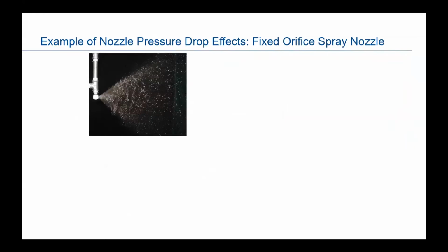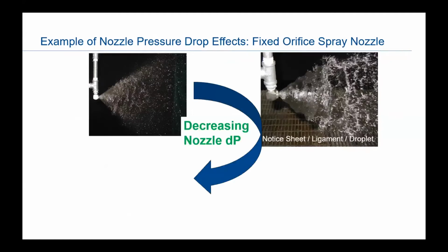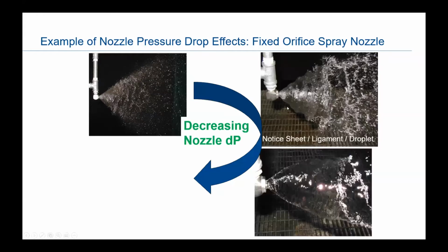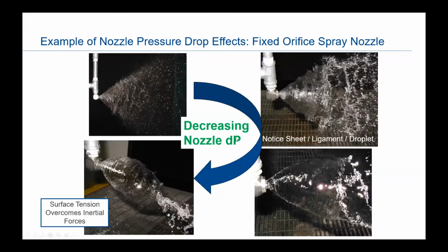So I'm just going to show you some fun pictures here of a nozzle. Again, this is a fixed orifice nozzle that I hope no one would ever install in a reheat Attemperator. This would be a terrible idea due to rangeability, but it really makes the point of what happens to a nozzle as you decrease the pressure drop. And really that's by decreasing the spray flow, assuming constant conditions on the steam and water side. So what starts out as a relatively good spray, although nothing like what you'd want to put in an Attemperator, starts to collapse on you as you decrease the flow further and further until eventually the surface tension in this particular nozzle can overcome the inertial force trying to break it apart, and it just collapses on itself.